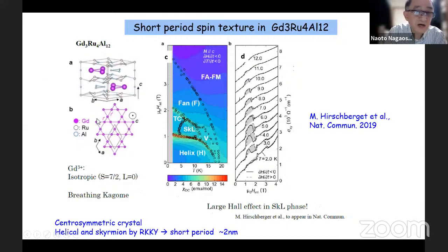So that is achieved by these materials, a little bit complicated, but this has an inversion center. And then the Dzyaloshinskii-Moriya interaction is irrelevant in these materials. And the helix is given by the RKKY type interaction through the conduction electrons. And then the typical spin structure has a 2 nanometer scale. And actually, I will be back to this topological Hall effect later, where this skyrmion lattice phase is identified. But we are interested in this helix and this transverse conical state.